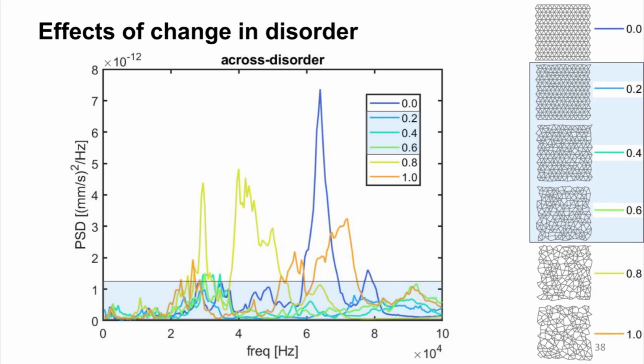So looking at the scale of these, the higher perturbation strengths could be used to change the location at which the higher amplitude peaks appear, and these peak amplitudes would be comparable to that of unperturbed lattices, whereas some of the intermediate disorders could be used to suppress the peak features and not allow vibrations to pass through the material. And so that tells us that disorder does form a control parameter for material properties, and we could use it as a tuning parameter.